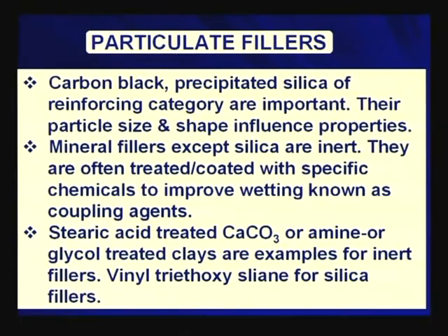Can you tell me the source of fatty acid? Source of fatty acid? Vegetable oil. Vegetable oil, sir? Glyceride esters of fatty acids, triglycerides of fatty acids. So, those fatty acids can be taken from or extracted from oil, and that fatty acid can be dissolved in a solvent, dilute solution, then make a spray coating on these filler particles. What will happen? Solvent will evaporate out, and there will be a thin coating of stearic acid or this fatty acid on the filler particle. So, it will be an organically modified filler, and that can easily be blended with polymer.